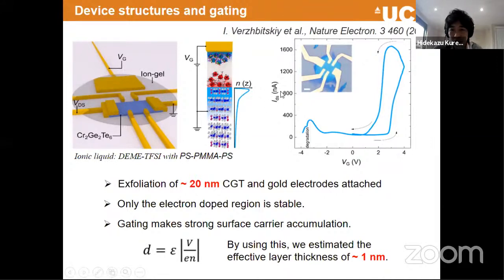And this is the source drain current as a function of the gating voltage. You can see at the beginning, it's almost insulating. There is no current there. But once we drive it and apply a reasonably large electric voltage, then we can increase the source drain current. And then going back to the bottom, you can see that if we try to go back to the opposite side, we couldn't achieve this because of some chemical reaction happening. I just mentioned that on this side, we are saying that this is an electron-doped regime. So we focus only on this electron-doped regime for our study.